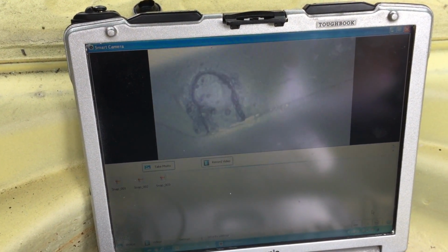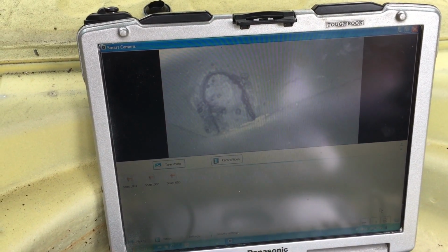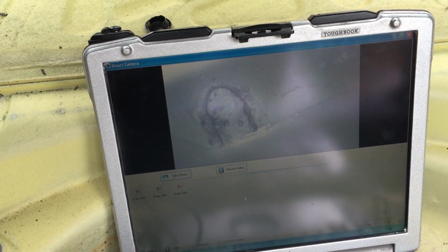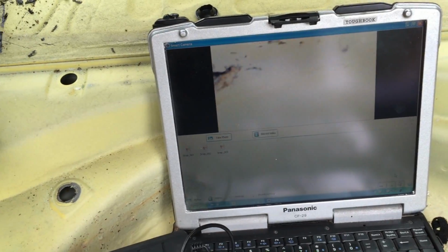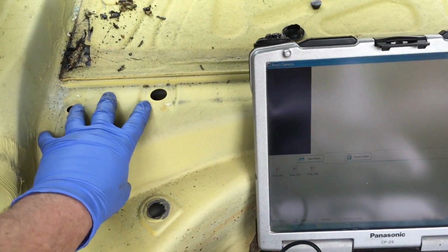on the 3-panel connection. That spot weld there has got a crack all the way around it, and 2 cracks going out to the edge of the panel. So it's not likely to travel anywhere, but it really needs to be addressed because there's 3 panels there that aren't attached to each other anymore, and also a crack, and you don't really want to leave any cracks anywhere at all on an E46. So we are going to need to take this corner off here.